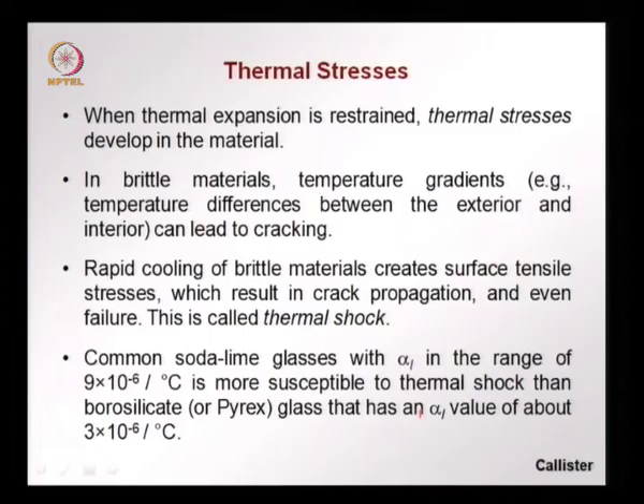These thermal stresses can also occur due to temperature gradients. Suppose you have the exterior of a body being much cooler or much hotter than the inside, a temperature gradient is set up, and this can also lead to cracking. Thirdly, we can have something called thermal shock, which can also create problems. Suppose we have a brittle material, say glass, that is very rapidly cooled, then you have very rapid contraction of the surface,